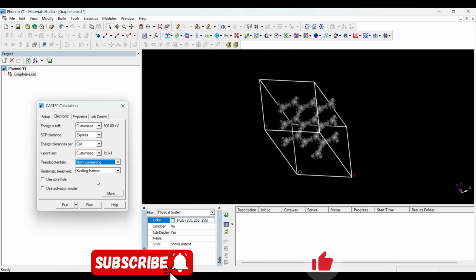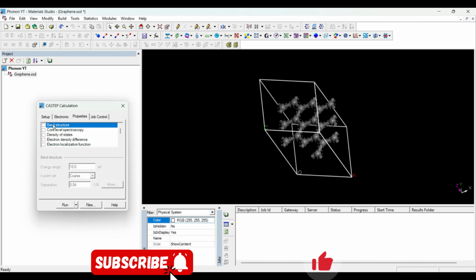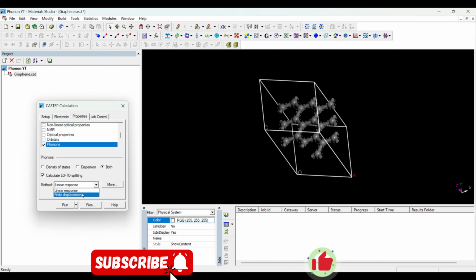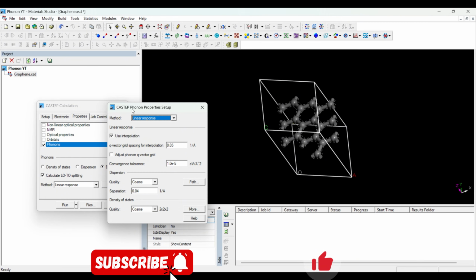And this is very important. Choose norm conserving pseudopotential here. Click band structure, density of states, and then phonons. There are two options, dispersion and DOS. You can choose both as well. Linear response is for small unit cells and periodic structures, and finite displacement is for big supercells. So I will choose linear response.